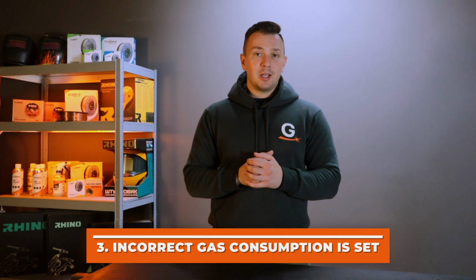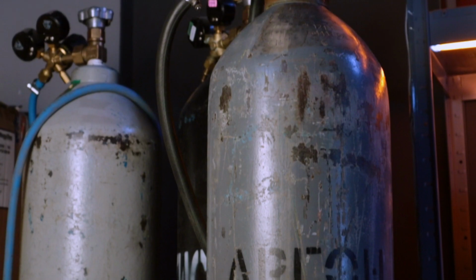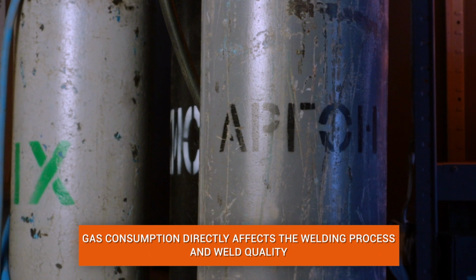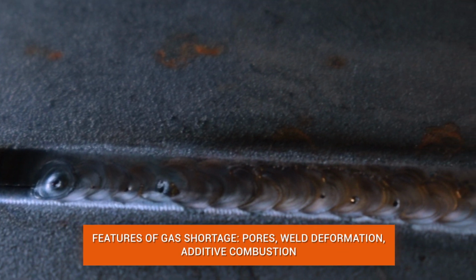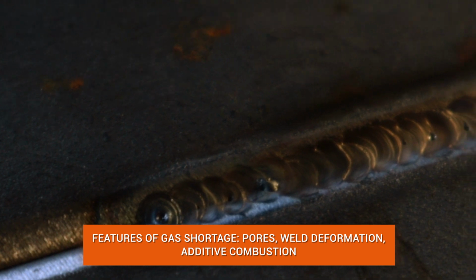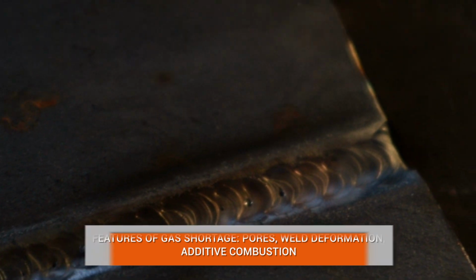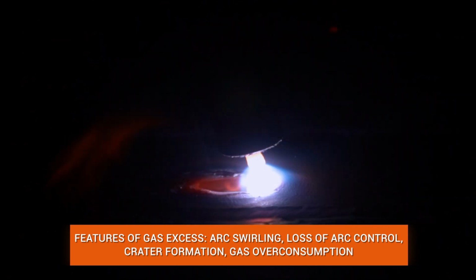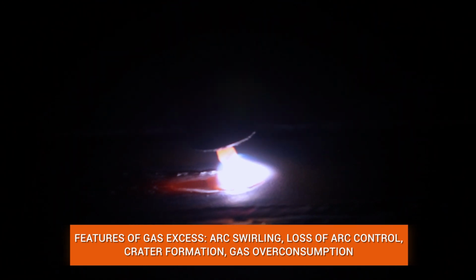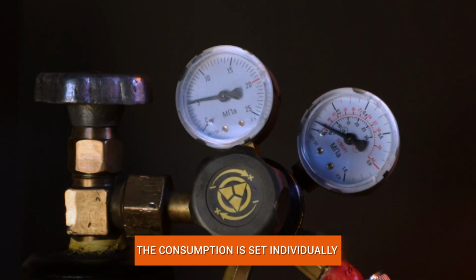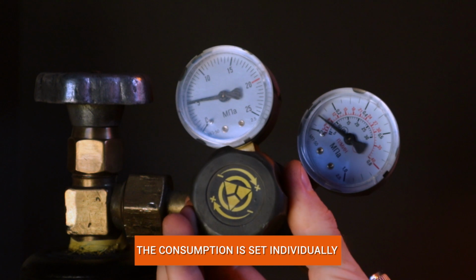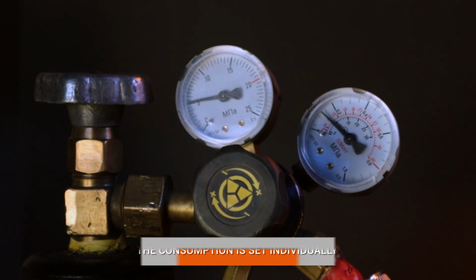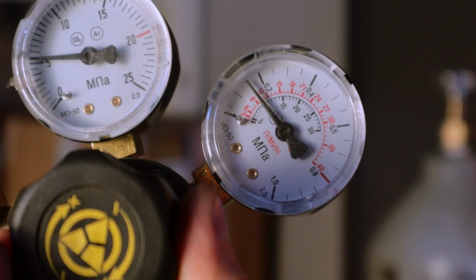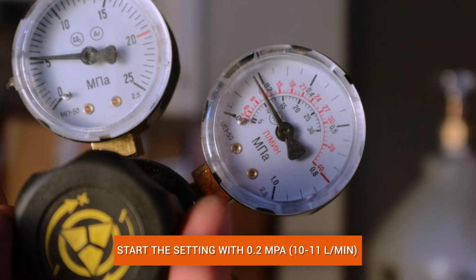Third error. The wrong shielding gas flow rate is selected. It is important to select the correct gas flow rate. If you set a lower gas flow rate than required, the additive and the welded structure burn, which in turn damages the quality of the weld. If you use more gas than necessary, the welding arc swirls, which leads to a loss of control over the welding process. The gas pressure and flow rate should also be set by testing and checking that the gas comes out evenly when pressing on the welding torch. This will help to save gas during operation. We recommend starting with 0.2 MPa when pressing the torch button.